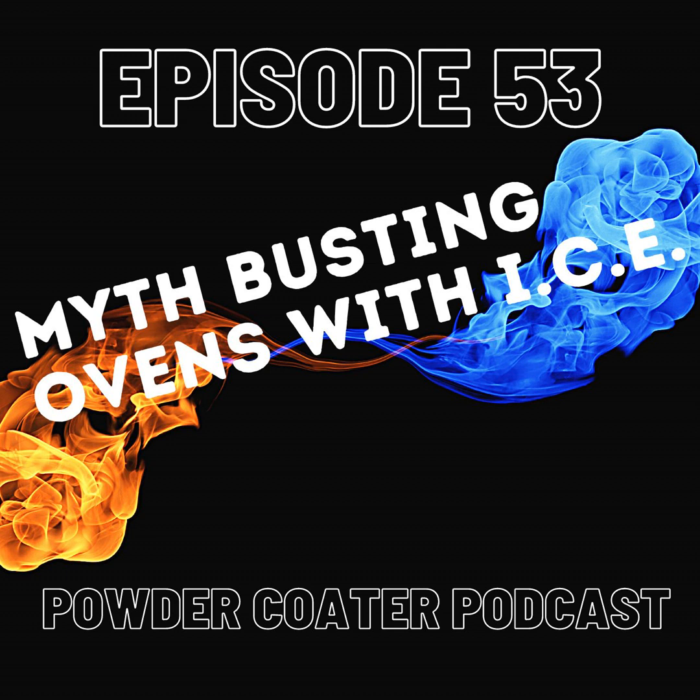But when we first built the large oven way back 10 years ago, we had this circulation system in there. But what my husband found was when you circulated it, maybe the fan was going too fast or circulating too much, it would cause a lot of debris to kick up and get into, say we were doing a flat panel or a gate or something like that. It would kick up a lot of dust and stuff like that in the oven, and it would end up in the finish as it was curing. So we decided to not do that with this new rebuild that we did here.